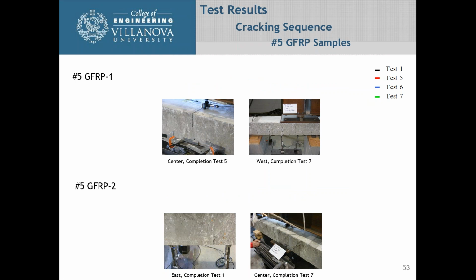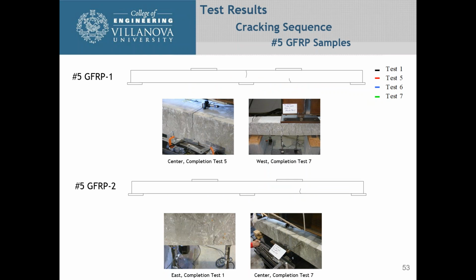So let's take a look at the GFRP bars. How did they react? At the end of test 1, you had much deeper cracking at the negative support on sample 1, and you started seeing cracking underneath one of the locations of load on the west side. After 100,000 cycles, you really didn't see much more additional cracking.